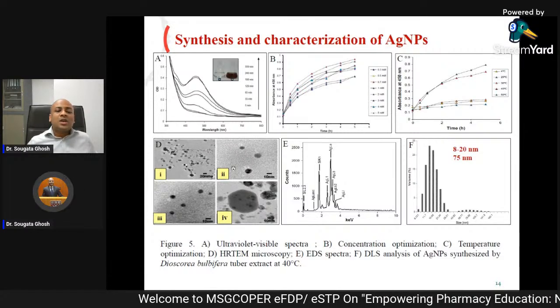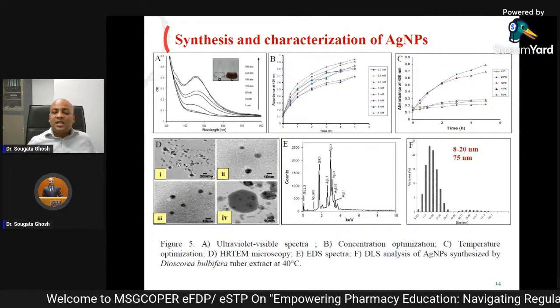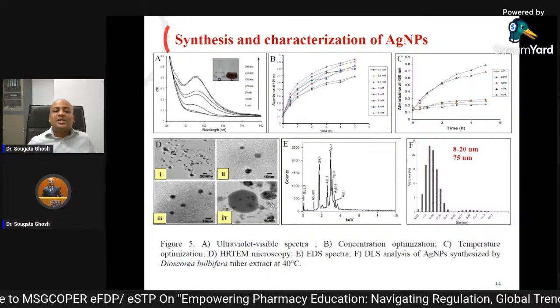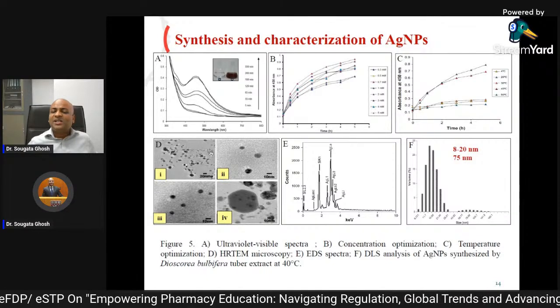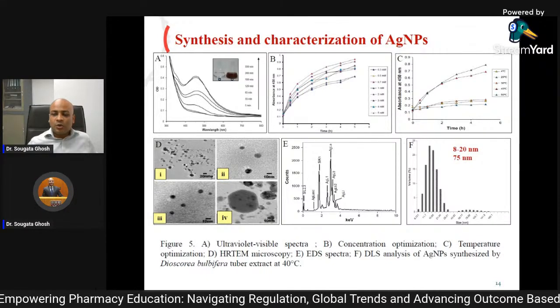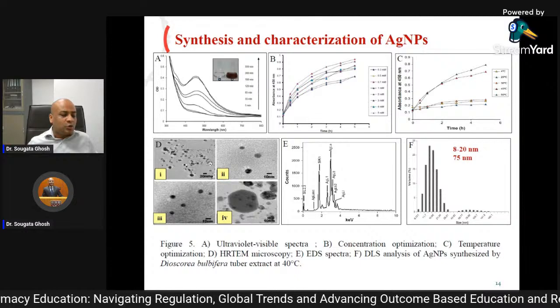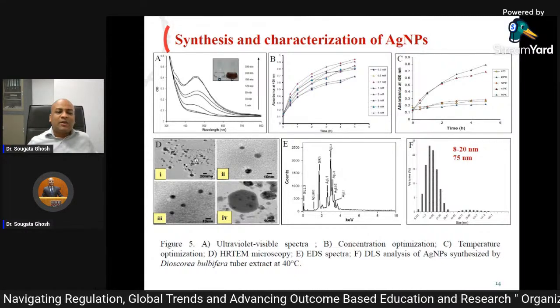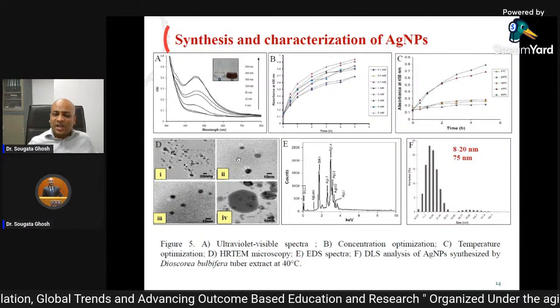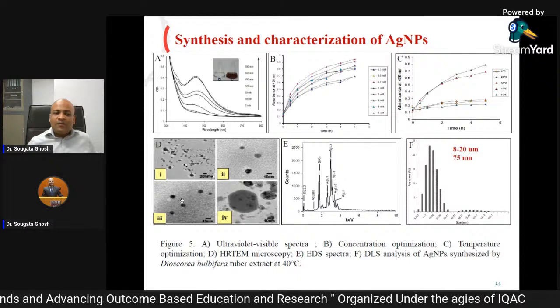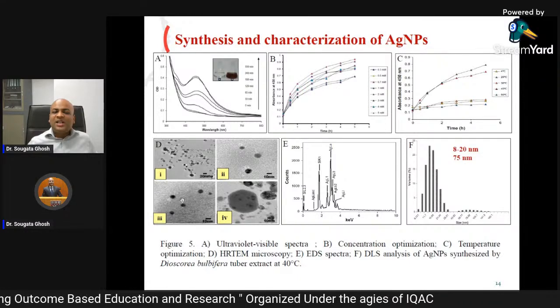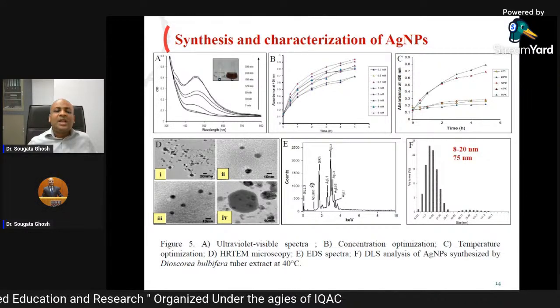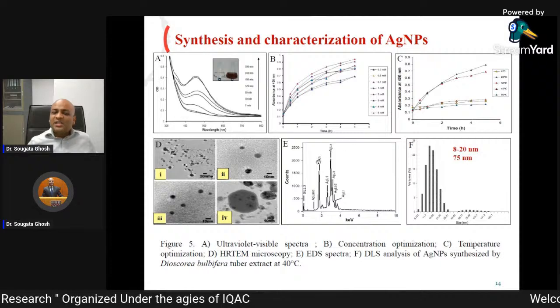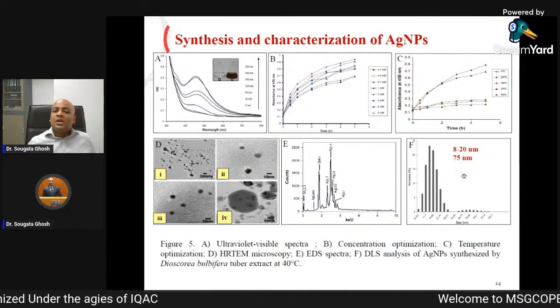And we did HRTEM, high resolution transmission electron microscopy, as these nanoparticles are not big like gold. So we found that there are very, very small spherical nanoparticles, which are around 10 nanometers. And we confirmed with EDS that there was indeed silver.